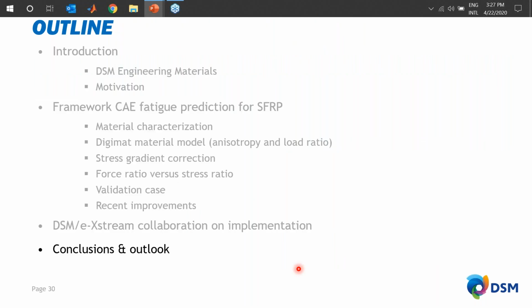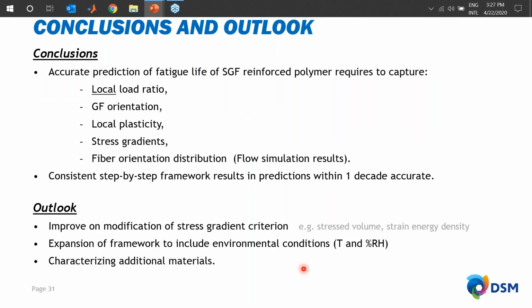And that brings me to conclusion and outlook. So I hope that I showed you, at probably high speed, that for accurate prediction of fatigue life of short fiber reinforced polymers, you need to look at the local load ratio. You need to take into account glass fiber orientation, local plasticity, stress gradients, and the fiber orientation distribution. But if you do this step by step, you end up within that 1 decade accurate. And we have some further steps, but with that I would like to conclude.